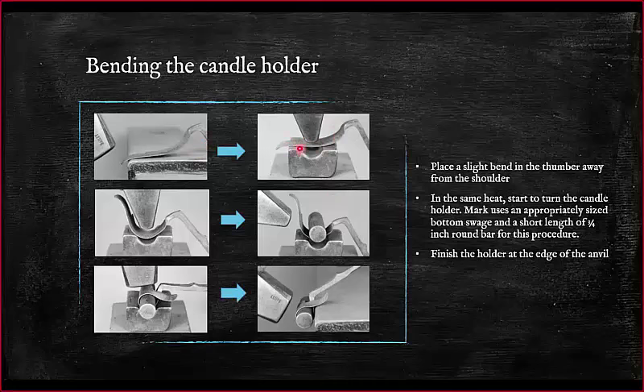But this is the beauty of making your own bottom swages, is that I can make one with sharp corners, I can make one with relaxed corners, however I want it to be made. And I have a number of blanks sitting ready to be manipulated at any one time. Now I'm forging in the middle. At some point, the thumber is going to interfere with the hammer, and I'm obliged then to work on the outside of the bar. Notice now I put a mandrel in, a piece of 3/4 inch bar to represent the candle. And then I'm going to close that as best I can. Think of me moving the stock so I'm rotating the candle holder in the bottom swage. And you'll see how the thumber now fits over the top of our corner number three because we cut out enough material.